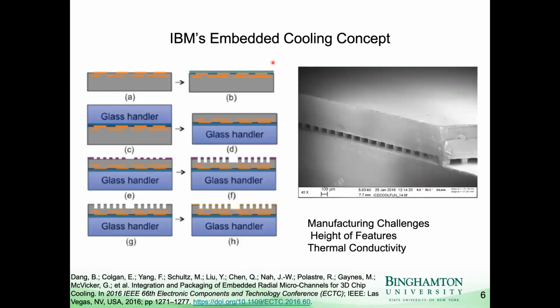For one, it's kind of complicated. It requires silicon photolithography, which is not cheap. Another issue is there's a practical limitation to how deep a trench you can etch. It's a slow process. Another issue is the thermal conductivity of silicon, while good, isn't quite as good as copper or some other materials like silver.